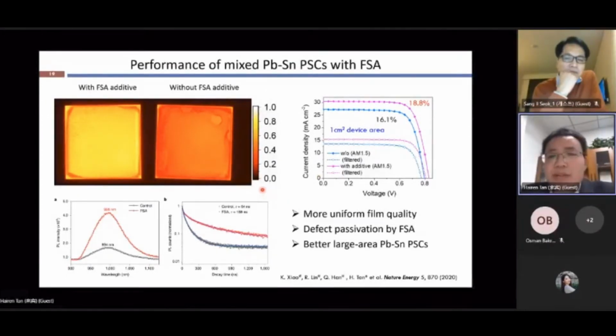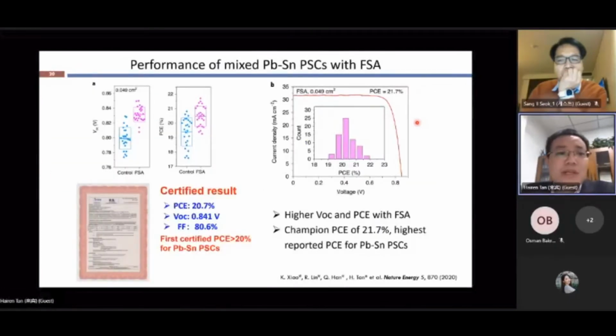Due to these three benefits, we can see that even for 1 square centimeter area devices, the efficiency is increased from 16% to almost 19%. And also due to the grain surface passivation, even for smaller area devices, the VOC, the open circuit voltage, is increased considerably, so that we can get a higher average efficiency. So the best efficiency for single junction devices, we can increase from the previous 21% to almost 22%. And we sent one device to Newport for certification, and we know that certification of tin-based perovskite solar cells is quite challenging, but we still managed to do that, and we got a stabilized efficiency of 20.7%.